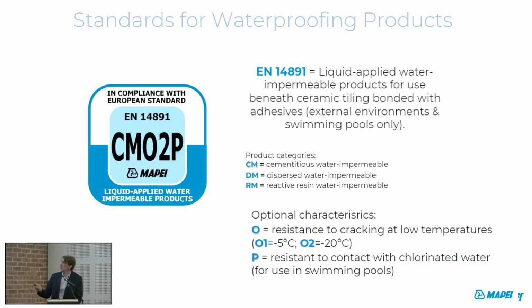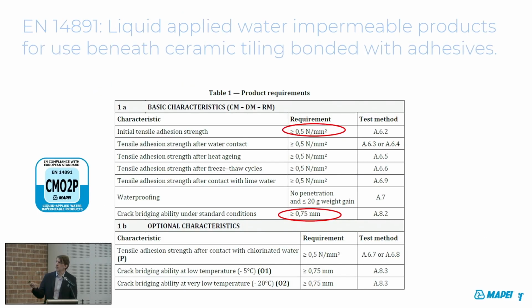And it can also be resistant to contact with chlorinated water, eventually close to the sea or close to the lake or close to water contaminated by chlorinated elements. So this kind of classification can make the difference between a certified, qualified product and a homemade waterproofing system. The performances are also defined in our technical data sheet according to the specification of the norms. We see crack bridging ability under standard condition because we have to test it in different conditions. We propose clearly the value of the deformation of the material, and the initial tensile adhesion, how much it can fix on the substrate.